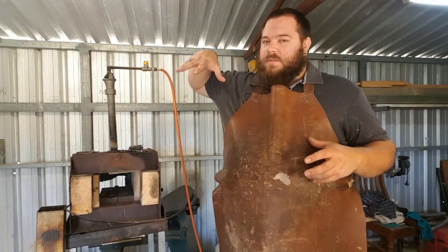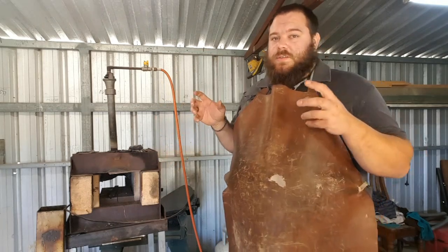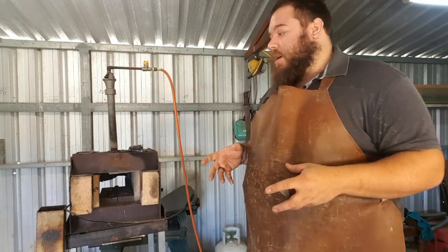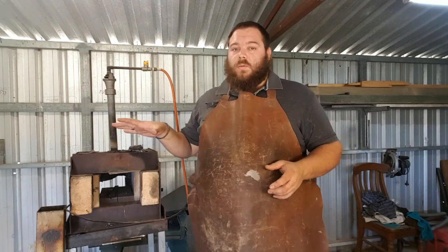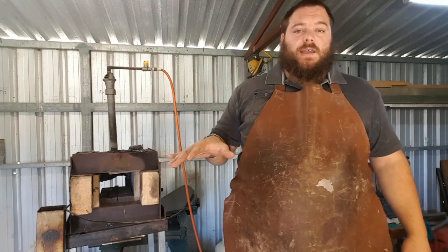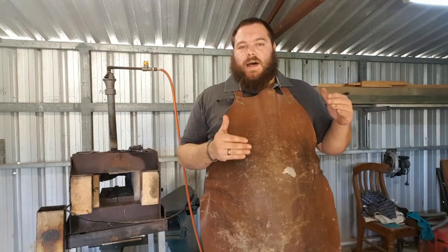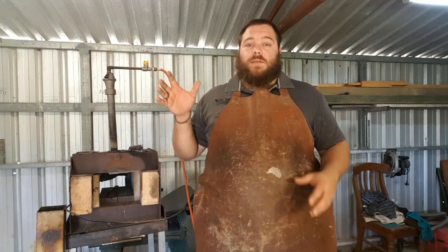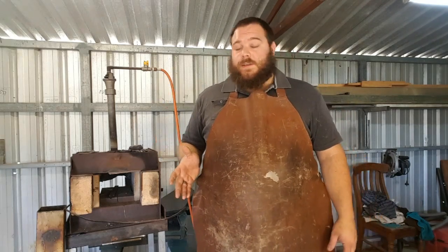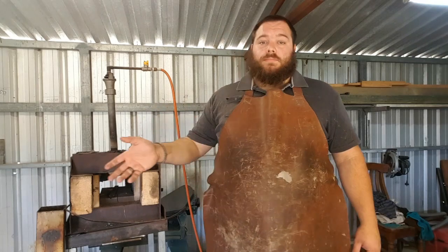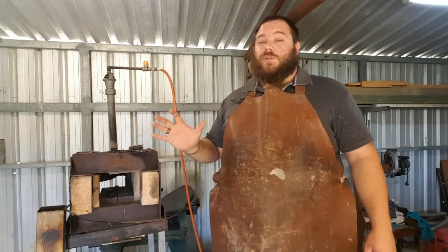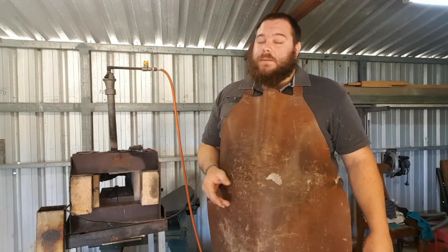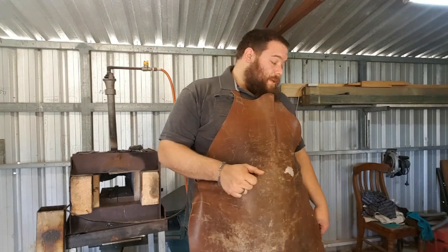The big problem with medium speed quench oils is that if you're using super high carbon steels or shallow hardening steels like W1, W2, 1095, those high carbon steels may not get as hard as you will get with a high-speed oil like Parks 50. That's why I want to get a high-speed oil eventually, because I use a lot of really high carbon steels, and Parks 50 would be amazing for that.